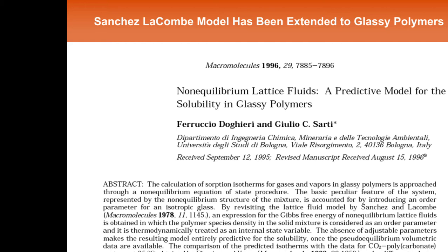And there's not much daylight between the curves and the data points, between the pure gas data and the gas mixture data. That is, butane sorption into silicone rubber is largely independent of any methane that's there. Now we're going to see in a moment, remember these solubility coefficients being in the hundreds and sorption levels in the 40, 50 cc's per cc range. Methane is much less condensable than butane, and so its sorption, even at high pressure, these are 2% mixtures of butane in methane, right? So 98% of the gas on the outside of the polymers is methane. And then as the pressure of that mixture ramps up, you see more butane sorption, but it's almost in line with what you see in the pure gas case.